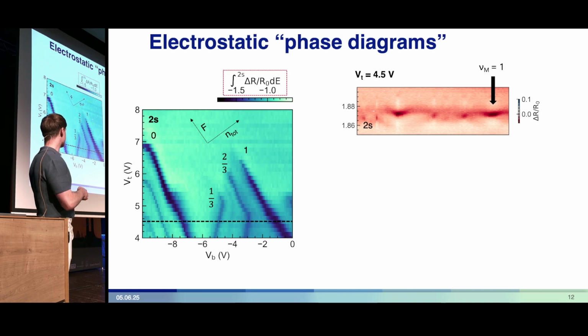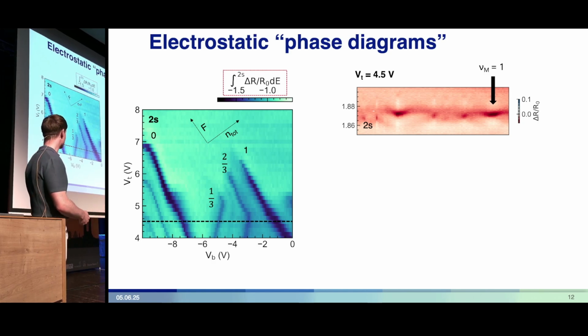An electrostatic phase diagram is just a map of the 2D gate parameter space, where at each pixel we take a spectrum and extract some information from it. For example, here's just the integrated strength of the 2s exciton. Everywhere you see a dark line in this electrostatic phase diagram is a place where there's a correlated insulator or an insulating, incompressible phase.